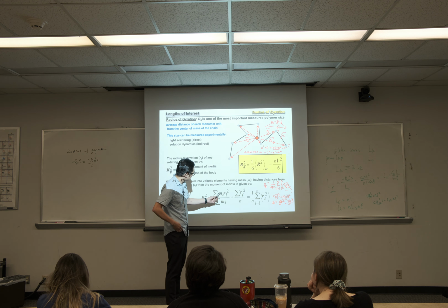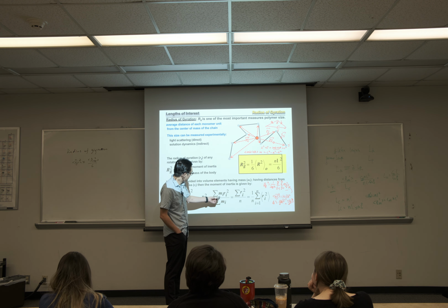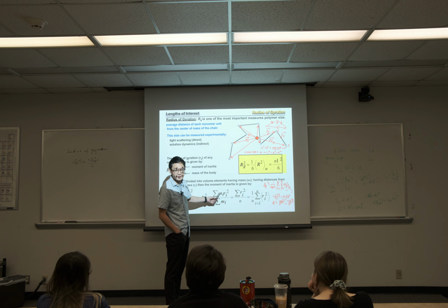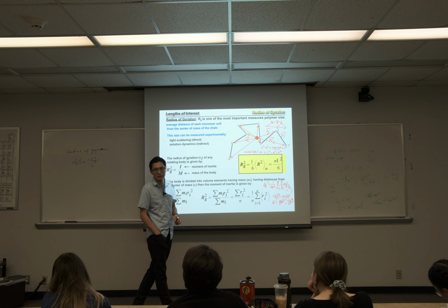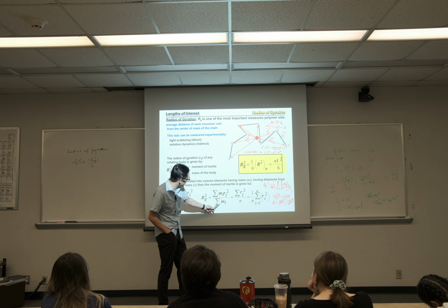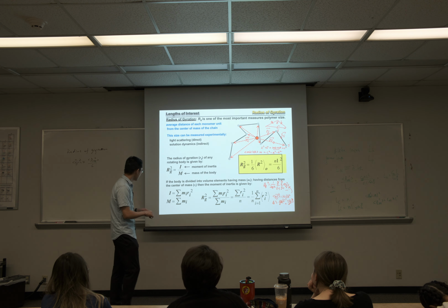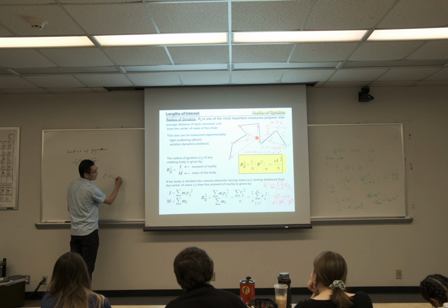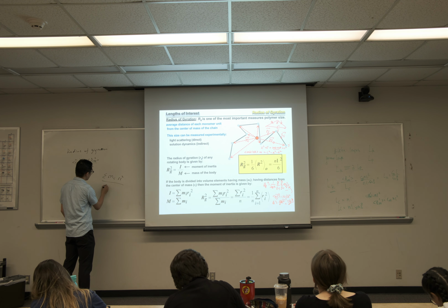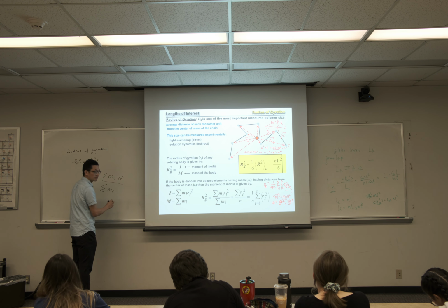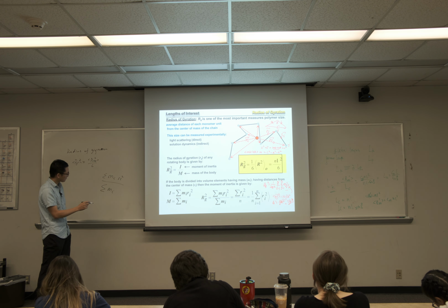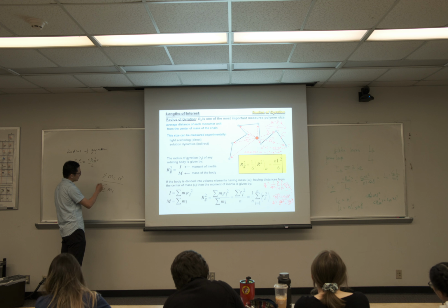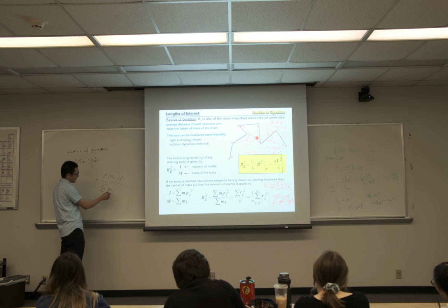On the top, we also have a mass, so we need to sum them up. But because the mass cancels out if we have a density term, we are left with just a summation of Ri square, which is vector square. Does that make sense? So basically the bottom summation is basically N. The mass Mi, let me write here, Mi Ri square divided by summation of Mi. So if we know the number of bonds, we can add all of them together.